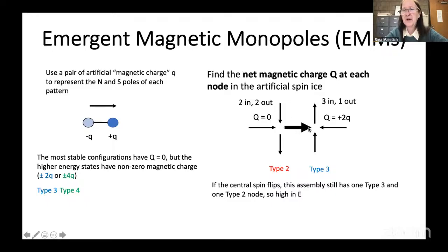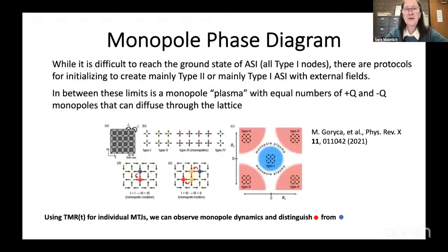If you imagine what happens to the central spin that has interactions, part of a type 2 node and a type 3 node, if it reverses thermally, now this node is type 3 and that's type 2. So it's going to be in a high energy state. And the only way that it can relax is if one of these side spins, one of the neighbor spins, also flips. So that could lead to fast dynamics. There's been some very nice work done by Chris Leighton's group looking at square ice, traditional ice, and working out a phase diagram where, depending on the field that you apply in the X or the Y direction, you can initialize your ice to have mostly type 2 nodes. Lots of papers have been written about how to use AC demagnetization to get mostly type 1, but it's actually quite tricky to get a true ground state.